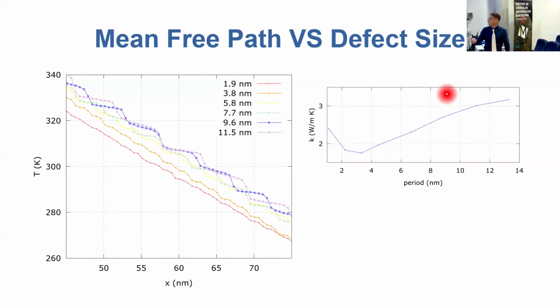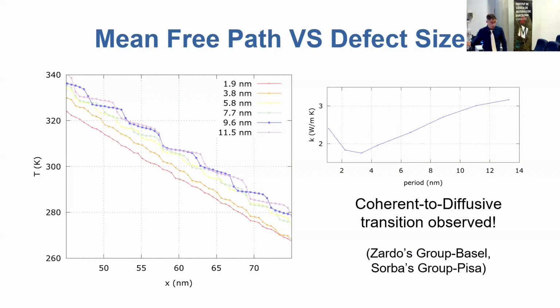Then at very long periods, the phonons will experience a sequence of interfaces and the thermal conductivity will scale linearly with the inverse interface density. In between, there is a minimum in the thermal conductivity, which corresponds to the transition zone between the coherent and diffusive transport regimes for the phonons. It is very interesting that this transition has been observed in the experiment as well, and it's going to be published, hopefully soon, in a paper which we are working on with Zardo's group in Basel and Sorba's group from Pisa. So this has been observed in the experiment and also in our simulation, so we are happy with that.